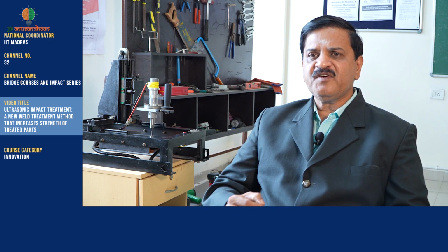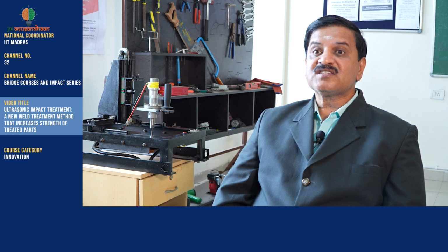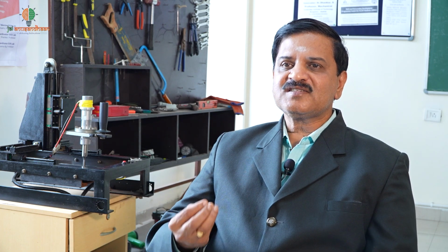after the impact test was done, we took the samples to the laboratory where we tested for the residual stress before impact and after impact. What is the effect? The difference we could see from the results is that we were able to reduce the residual stresses by 40% effectively and efficiently, without altering the property of the material and without the strength getting reduced. The basic material strength and properties have been retained, and no damage has happened on the material, but the residual stresses got relieved by 40%, and that too it takes only 9 to 10 seconds to operate. Within that we are able to relieve the stresses to the required level.